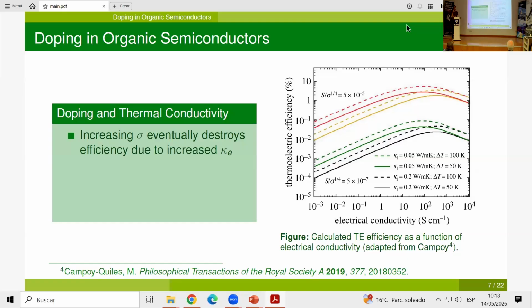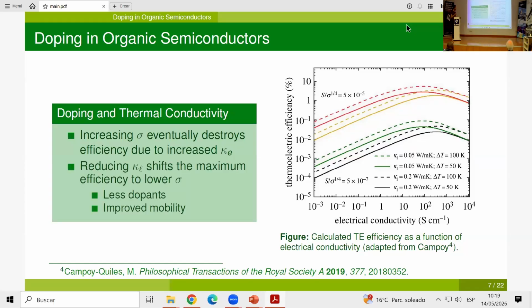Eventually, if we want to increase the efficiency of thermoelectric generators, we might think to increase the electrical conductivity, but this will also increase the thermal conductivity due to the increased electronic contribution to the thermal conductivity. So actually reducing the lattice contribution to the thermal conductivity is a good strategy to shift the maximum efficiency to lower electrical conductivity.